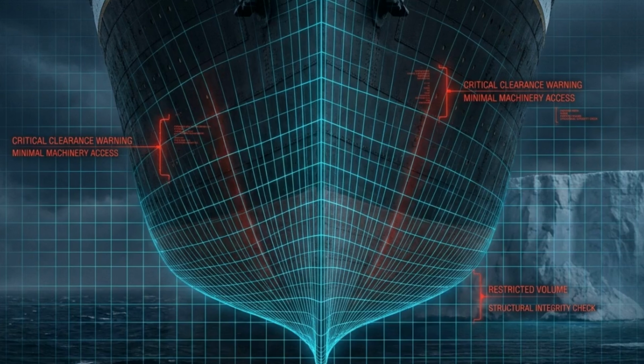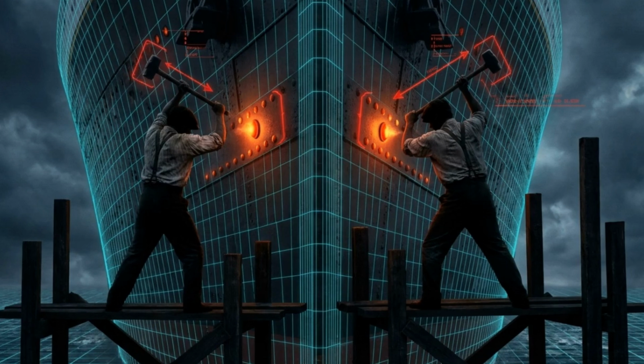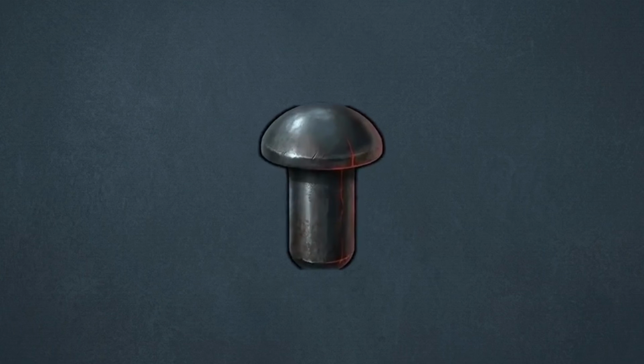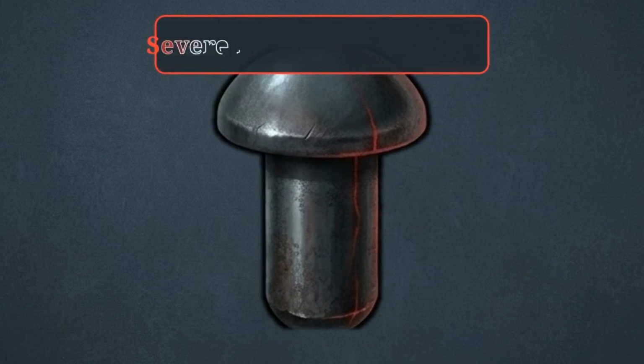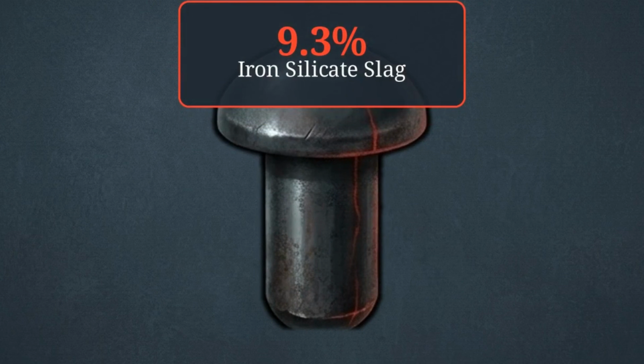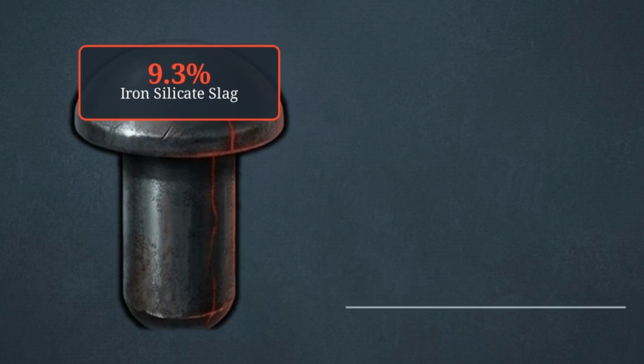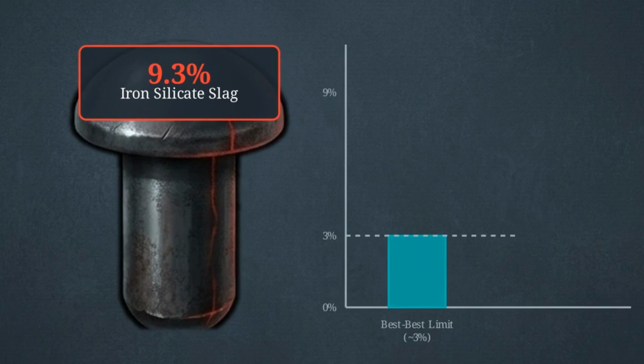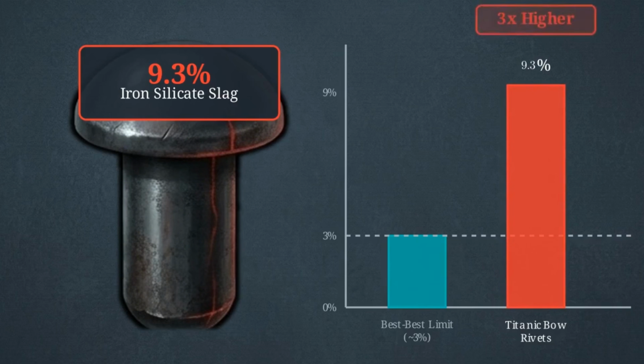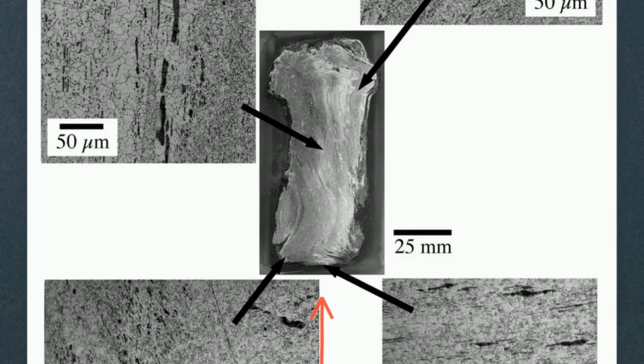Where the bow of the ship tapers sharply, the structural curvature prevented the use of large hydraulic presses. Instead, the shipyard used wrought-iron rivets that could be manually hammered into place. Metallurgical analysis by the National Institute of Standards and Technology discovered a severe microstructural flaw. These specific wrought-iron rivets contained an average of 9.3% iron silicate slag. This concentration of slag is 3 times higher than the specified limit for premium best grade wrought iron of the era. The manual installation process compounded this defect.